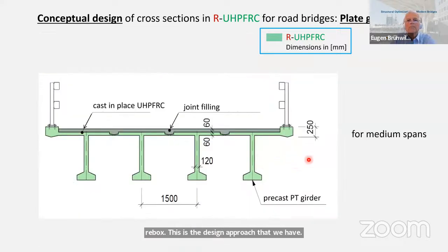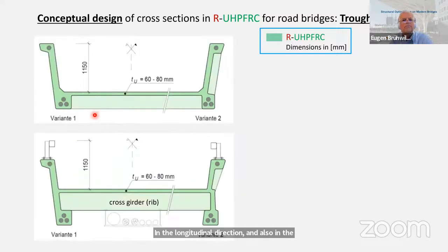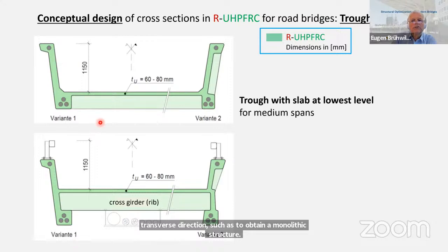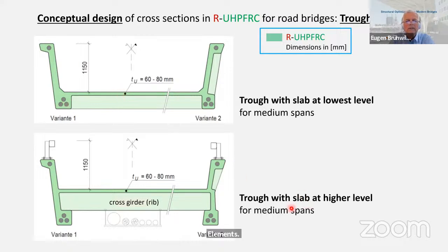This is the design approach that we have. Or when it comes to plate girders, we have here precast elements in bright green, and then on site we cast UHPFRC in place, fill all the joints in the longitudinal direction and also in the transverse direction, such as to obtain a monolithic structure. These are U-shaped cross sections, trough elements with slab at the lowest level, here at the higher level, always with the cross girders, transverse ribs, longitudinal ribs. Of course, this design with ribs has been inspired by steel construction.